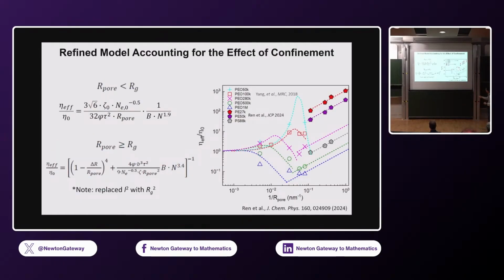And here's what we saw. So again, this is now inverse of pore, and here's the normalized viscosity that we obtain. So the filled symbols are our own results. The open symbols are the results from the other papers. Okay? What you see is that now by making those modifications or refining the model that I just showed you, we can explain this rise in the viscosity as the pore gets really, really small. Okay? We can also go back to the experimental results from the prior work, and what you see is that they also seem to see that increase, okay, when the pore size got very, very small for their own polymers as well. So this refinement now tells us that there are actually 3 different regimes, right?